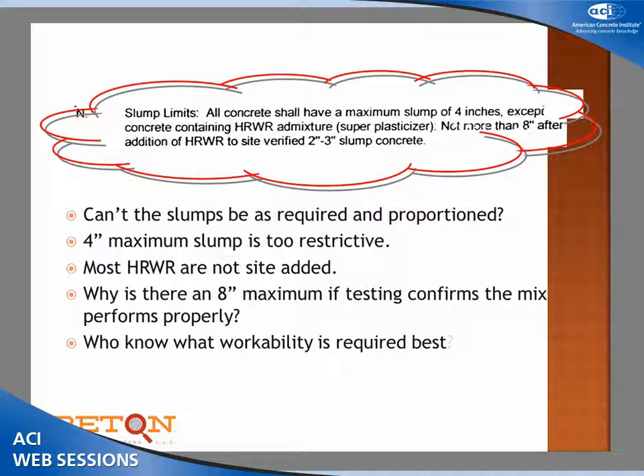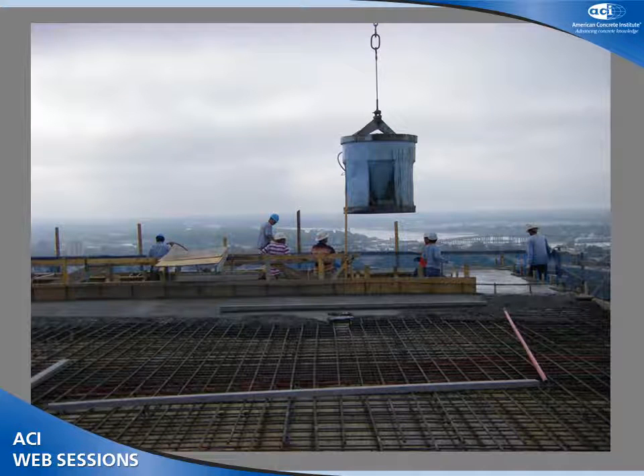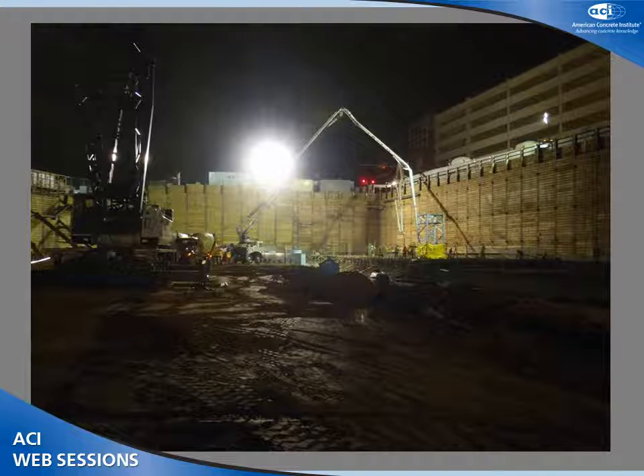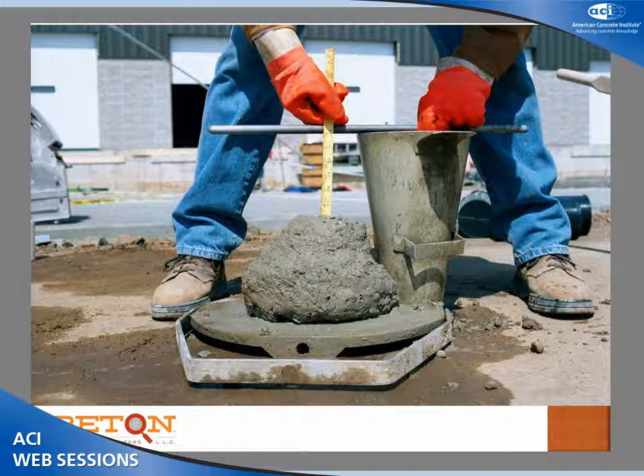Some of those concretes may not be pumpable, or worse, I might make them pumpable at a 2 to 3 inch slump. And then if I do that, I'm going to do lots of things that are going to cause cracking. Is the contractor going to be building like this? I don't know what's out in the distance, but it's much more interesting than the bucket apparently. Or are they going to be doing this? Two different concretes could meet the same specification but be placed differently. Stay away from slump. It's a means and methods.